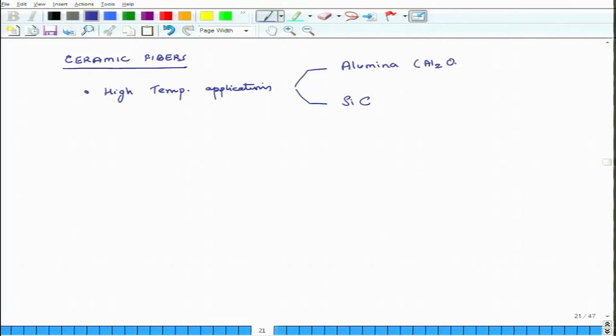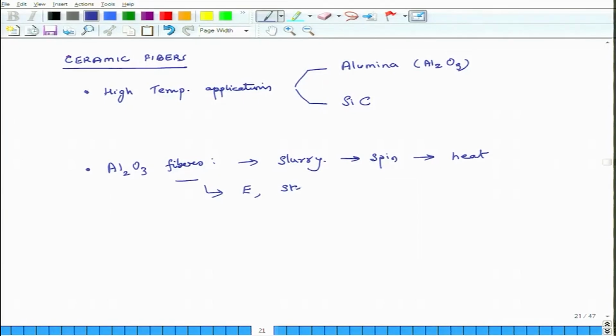So, this is Al2O3. So, very quickly, how are alumina fibers made? Al2O3 fibers. So, you have aluminum oxide, and from that you make a slurry. So, you mix it with the water and you make a paste, and through that paste you make a slurry, and then you spin it. You spin it, and then you start getting fibrous shapes, and while you are spinning it into fibrous shapes, you also heat it, and then you get these fibers. And these alumina fibers have shown, it has been shown that they can retain their mechanical properties, that is Young's modulus, strength, etc., as high as 1370 degrees centigrade. So, this is about alumina fibers.